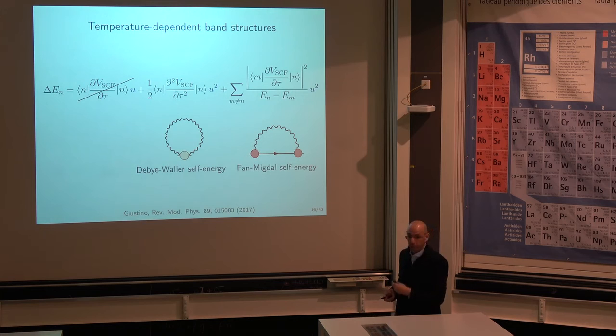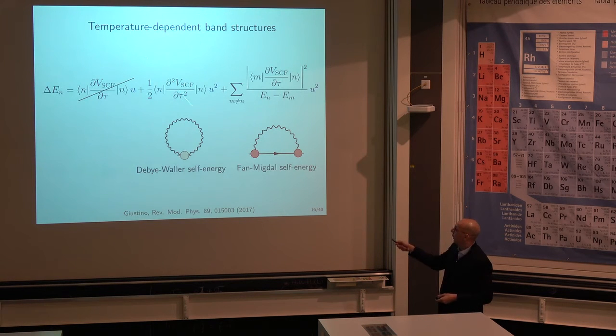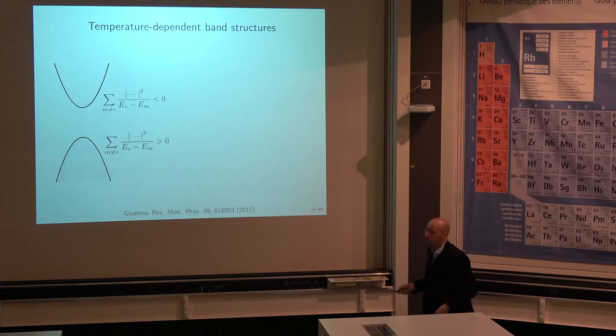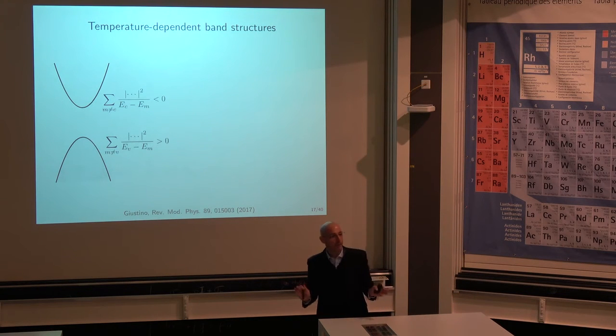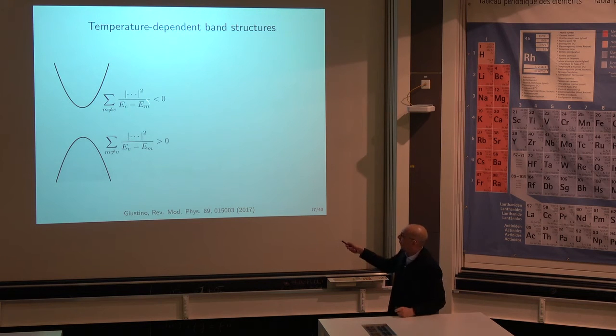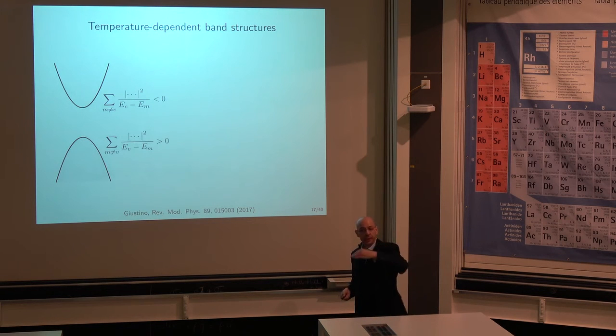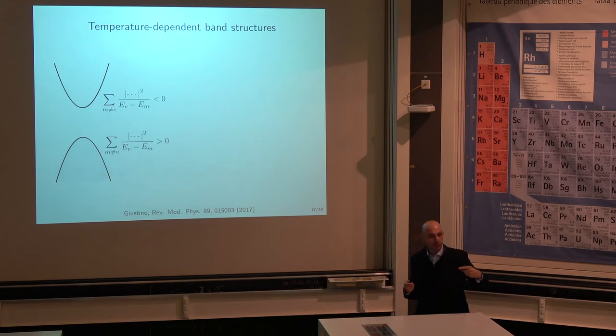Let me show you what happens if we use these equations. Let's forget this one for a second, and let me show you what happens if you just concentrate on this bit. You see the numerator is always positive, right? So let's see what happens to this term if you take a standard direct gap semiconductor and assume parabolic bands. Basically here, this summation, so the change of the eigenvalue, if I look at the conduction band bottom, the largest terms in the summation are those with the smallest denominator, right? So they will be the ones coming from energies which are very close to the conduction band bottom. But since the conduction band bottom is here, all the other states will be above, and this denominator will be negative, okay? So this is a negative number which increases with temperature in magnitude, okay? So this guy will go down with temperature. For the same reason, the valence band, since that's the opposite curvature, will have the opposite effect. So it's a number which is positive and will increase with temperature.